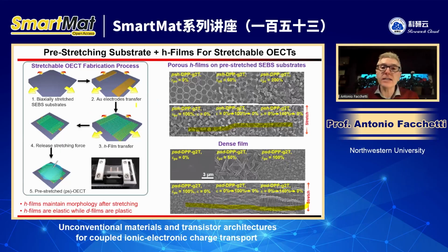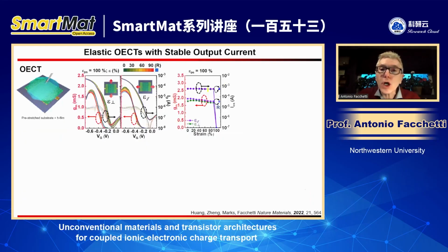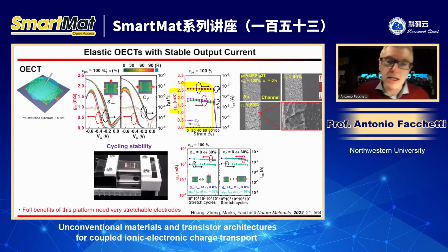And when you do that, only if you do that, the current does not change with the strain. Okay? This is not normalized current. This is Gm. It does not change because of the combination of the honeycomb plus the pre-stretch. And we did all the experiments about stability and things like that. This is not important. If you're interested, you can look at the paper. But really the key message is the combination of the pre-stretch and the honeycomb. If you do the same thing with the dense film, you will see a variation of the current because the film is plastic.